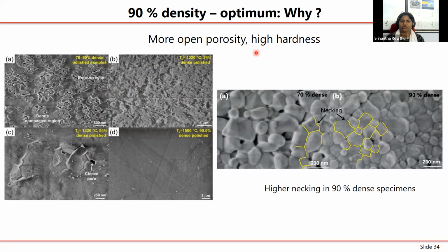But also you need high hardness, right? If it is a very, very soft material, then what can happen, especially in the 70% sample, is a lot of grain fracture, especially at the grain boundaries. We have thoroughly studied it; I am talking based on the study. So the grains are going to fracture, and that is going to lead to some debris. That means you are going to end up with third body abrasion. So that means you are going to have higher friction and higher wear rates.